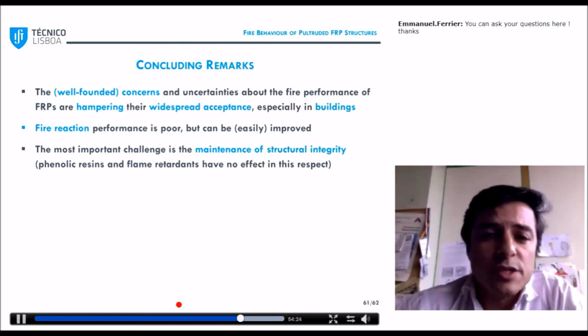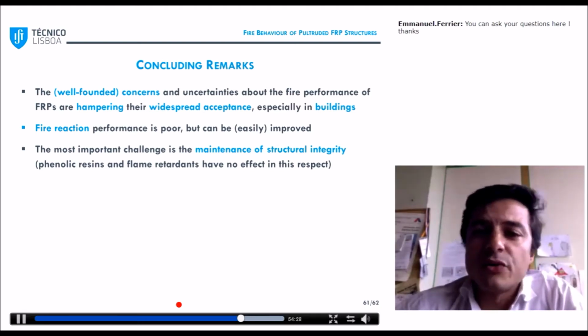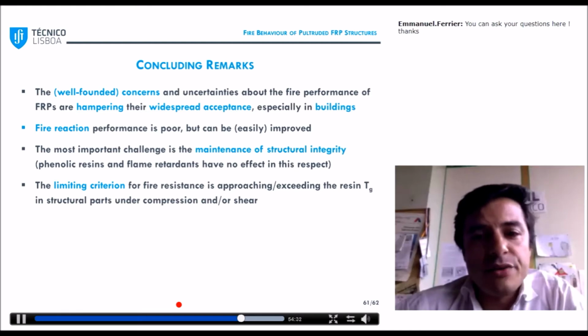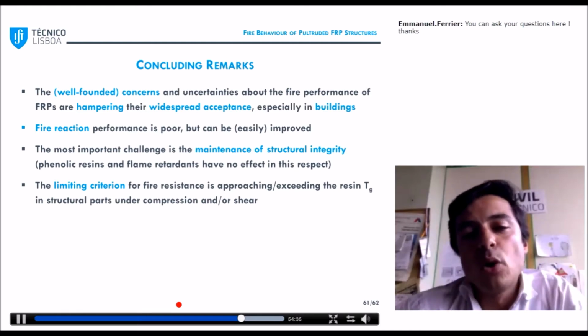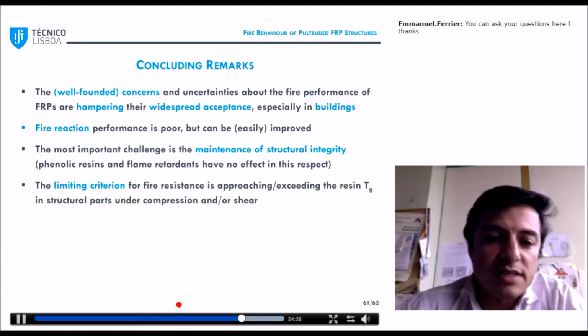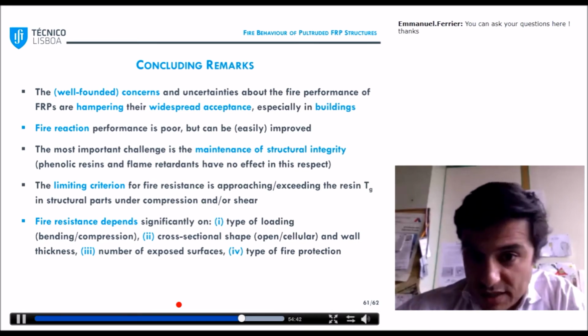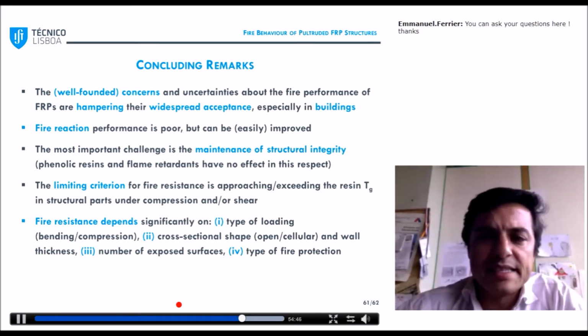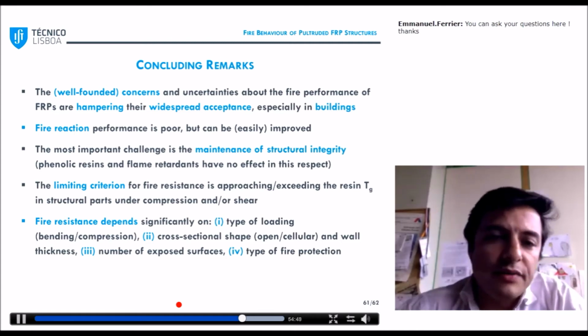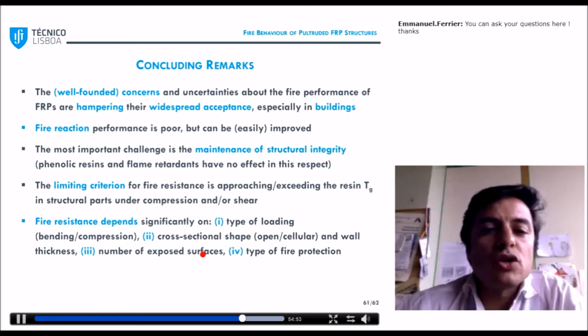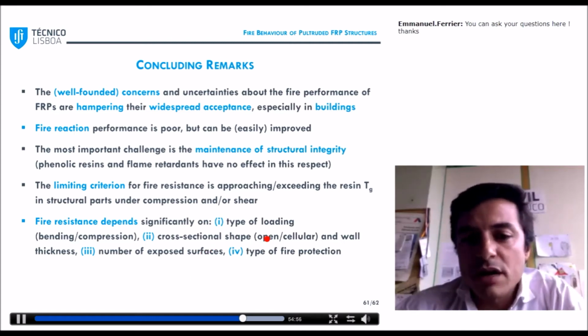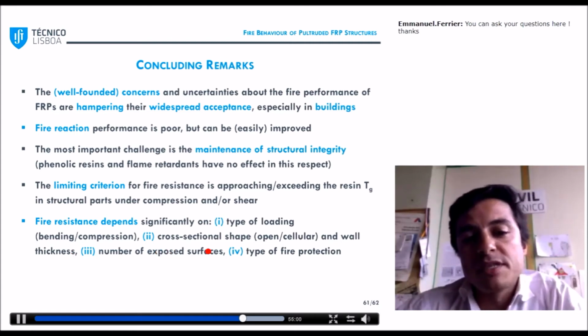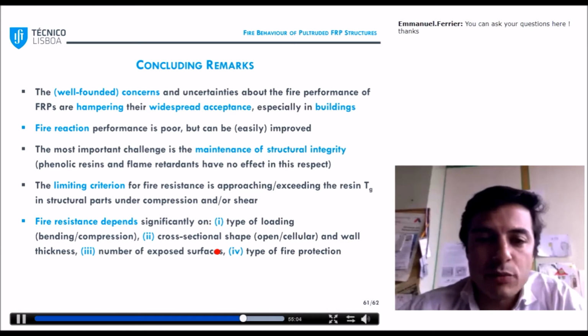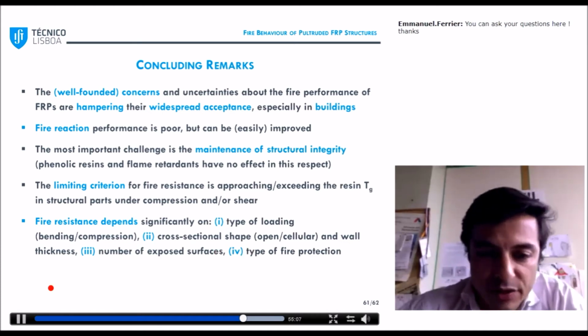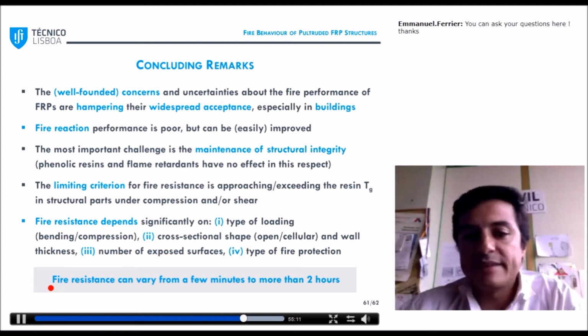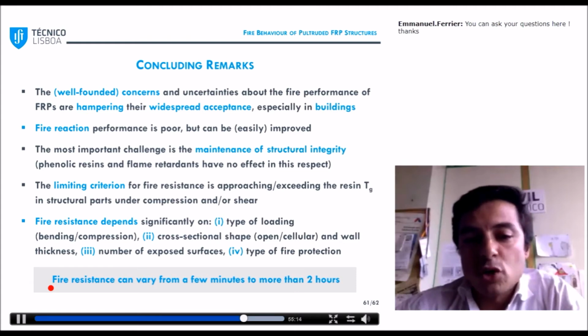And in this respect, phenolics and flame retardants are not really effective solutions. And the limiting criterion for fire resistance is really approaching or exceeding the glass transition temperature of the resin in structural parts under compression and/or shear, and not that much in tension. And for that reason, fire resistance depends significantly on the type of loading, either bending or compression, the cross-sectional shape, if it is open or cellular, and wall thickness, the number of exposed surfaces, so the building architecture here plays a very important role, and the type of fire protection. And therefore, depending on these factors, the fire resistance can vary from only a few minutes to more than 2 hours.